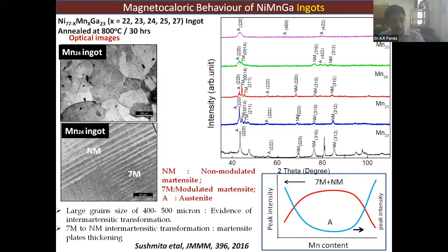These materials show quite a large grain size. Let me tell you that nickel manganese gallium has quite large grains, typically around 400-500 microns, and of course it involves a lot of intermartensitic transformations. You see that there is a lot of plate thickening in some places, and in other places the plates are much finer. These are basically the martensite plates. In the bottom optical images, you find the different martensite plates.